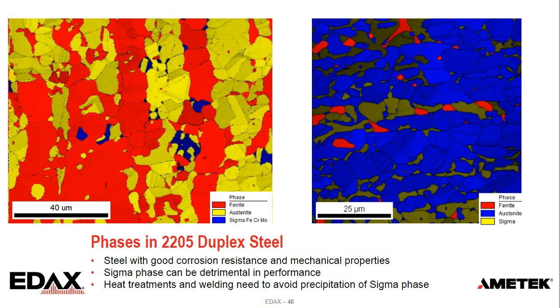I want to talk a little bit about looking at different phases in steel. Generally it's easy to think of steel as a single or dual phase steel. Oftentimes there's lots of other stuff going on in there. So I was talking about pipeline steel. This is a 2205 duplex steel used for its good corrosion resistance and mechanical properties. But if it has a sigma phase, it can be detrimental to this performance.